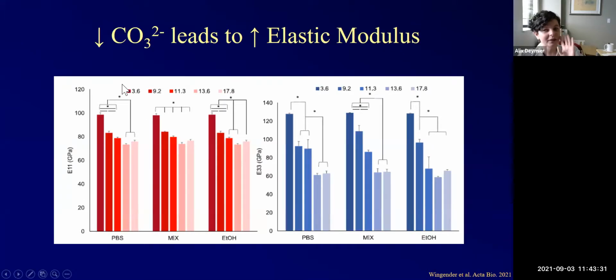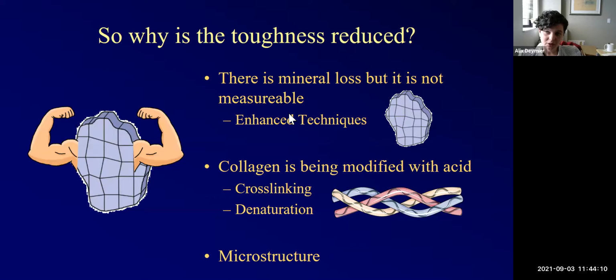And what we see is that, unlike my possible theory that the carbonate might be making these softer and therefore more likely to arrest cracks, the loss of carbonate actually leads to an increase in modulus. So you can see as I go to lower and lower carbonate levels, I have a higher and higher modulus, both along the C-axis and along the A-axis. So if my crystals are getting stiffer, that means my composite is getting stiffer, which means it's likely getting less plastic. And that doesn't explain the crack arrest. So why is my toughness going up if my crystals are getting stronger? And this is a question that we're still working on.